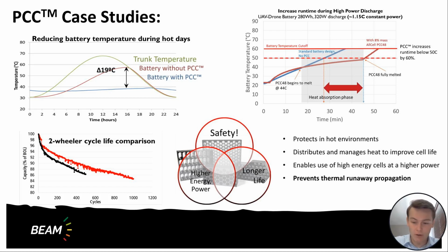One interesting benefit with this capability is that there's lots of applications that are sort of between a power versus energy cell, and a lot of manufacturers decide to move to the power cell so that they don't have, due to lower impedance, obviously you don't have as many thermal management issues when discharging at high power. But with the PCC, with its rapid heat distribution and absorption, we can actually transition those applications into an energy cell. And so obviously that provides greater overall energy in the pack. But another significant benefit is reducing cost, since energy cells are much more cost competitive and are produced at much larger volumes than power cells.